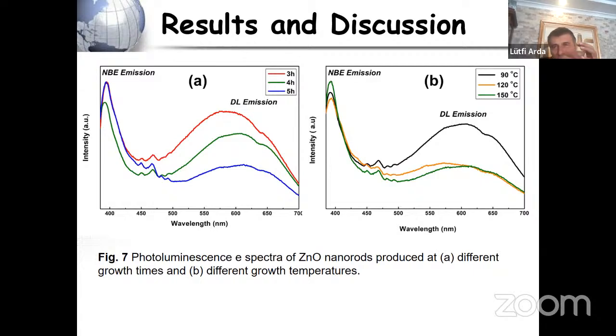The second dominant broad emission band, because this part is very important, and this is the center of my work, okay? The second dominant broad emission band is the visible region. The deep level emission is assigned to impurity defects, including oxygen vacancies, zinc interstitial, zinc vacancies, oxygen antisite, and oxygen interstitial in the zinc oxide crystal structure. These defects are divided into 2 parts. Zinc interstitial and oxygen vacancy are donors, and zinc vacancy, oxygen interstitial, and oxygen antisites are acceptors.